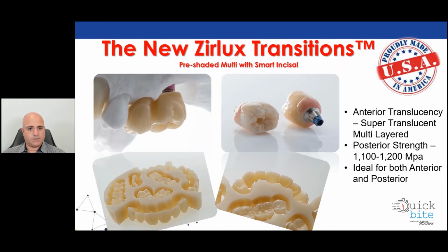But this particular zirconia, the transitions, has a posterior strength, a strength anywhere from 1100 to 1200 megapascals. Now, why the difference? The difference between 1100 and 1200 megapascal is that the further cervical it is, the more sintered zirconia particles there are. And then as you gravitate toward the incisal edge, you have more yttria component, and it is a little bit weaker, but still 1100 to 1200 megapascal is significantly higher than some of the other restorative options.